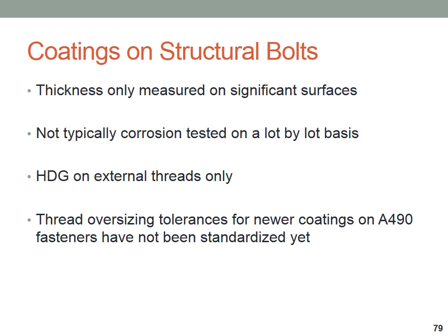Another thing to understand about coatings, thickness is only measured on significant surfaces. In the case of a bolt, that would be the head, typically on the flats or the top of the head. We don't really try to measure coating thickness within the threads. Coatings are not typically corrosion tested on a lot-by-lot basis. A lot of engineers over the years have said, well, let me see the salt spray test results on this. Typically that is done at the process level or proven out by the platers, and it's very rarely done on a lot-by-lot basis.